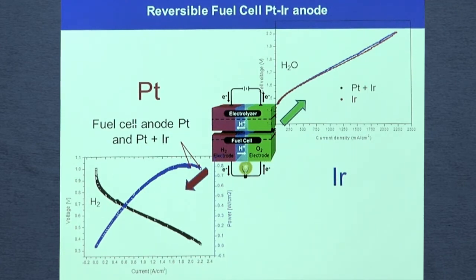Okay, now if we check this platinum-iridium double layer as a proton exchange membrane fuel cell, as a potential fuel cell, you can see that the quality of the performance of the cell is the same with and without iridium. So it's very similar again. Iridium doesn't help, but it's not worse with iridium. Which means that we can use this platinum-iridium multilayer as an anode of an electrolyzer and also as an anode of the fuel cell. And again, with relatively very low loading, because we checked that also with thin film platinum as a cathode. So we have loading which is maybe 50 times lower.